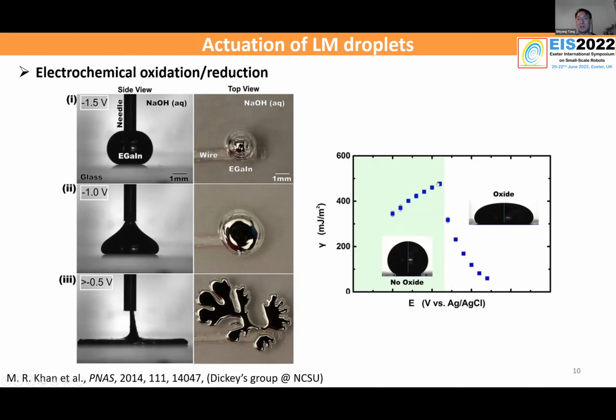So in this case, the oxide layer kills the surface tension and makes the liquid metal expand. The surface tension is near zero, so theoretically you have infinite surface area. That's the reason why these branches form. You can also reduce the surface by applying a reduction potential to restore its surface tension, and then it goes back to its original spherical droplet. So this is the second mechanism we'll be harnessing to form some of our actuators.